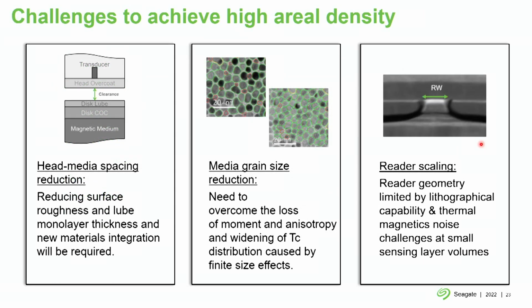Some of the challenges to being able to achieve this 10 terabyte per disk without changing the drive architecture are head media spacing. So as we reduce all of these geometries, if we don't move the head closer to the disk, then the resolution will not increase. The thing is, it's not just that we have the recording layer and then the NFT right above it. There are all of these protective layers on top of the media, on top of the head, in addition to the air-bearing surface that create physical space. And these layers have to be there in order to protect all of these different components. So we're trying to figure out what kind of novel materials can be used. And that's a pretty important and critical research issue for us, reducing head media spacing, because even if we reduce all of these geometries, that could very well be a limiting factor.